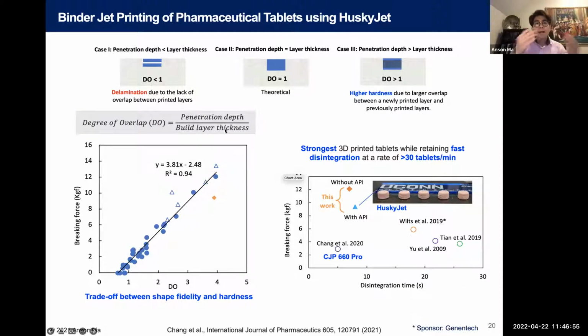Essentially, the higher this value, the more liquid binder per powder ratio you have. And you can see a beautiful linear regression here showing how strong your tablets are depends on this process parameter. We also benchmark our work against other people's work. By being able to control all these process parameters, we were able to make the fastest disintegrating tablets that disintegrate in 10 seconds and yet have reasonable breaking force. For commercial tablets, we're talking about 10 to 15 kilogram force.